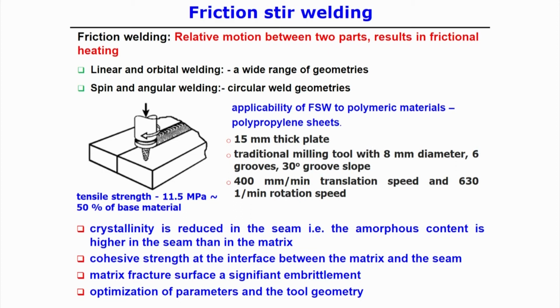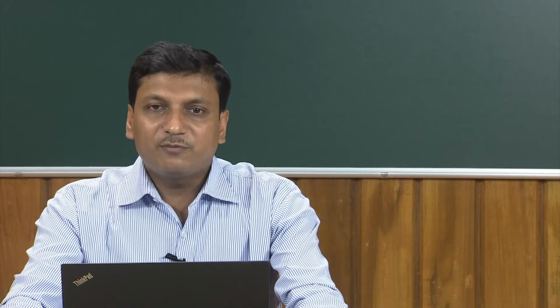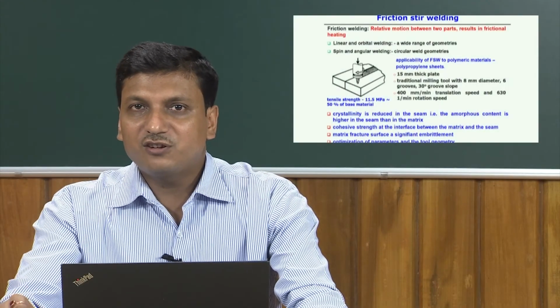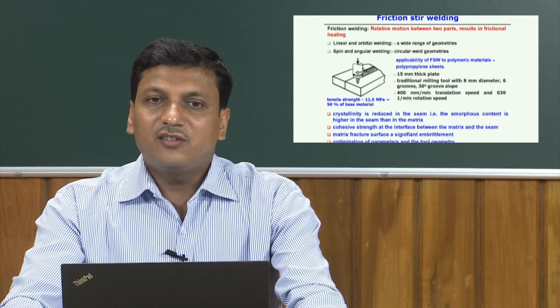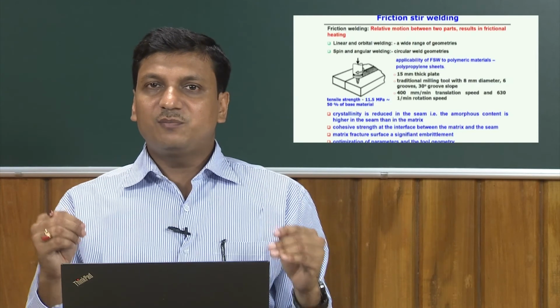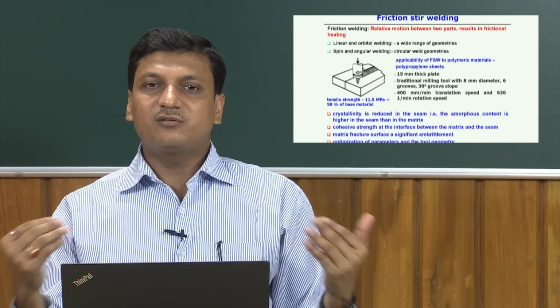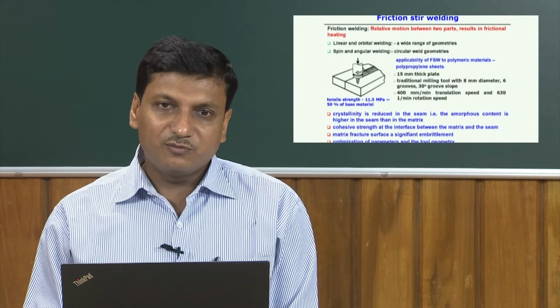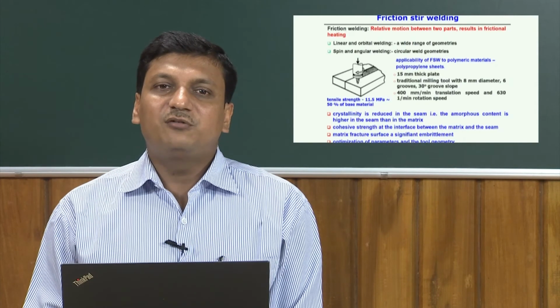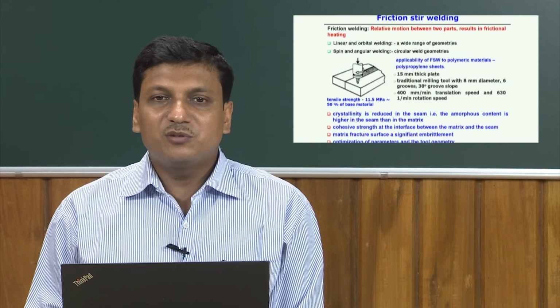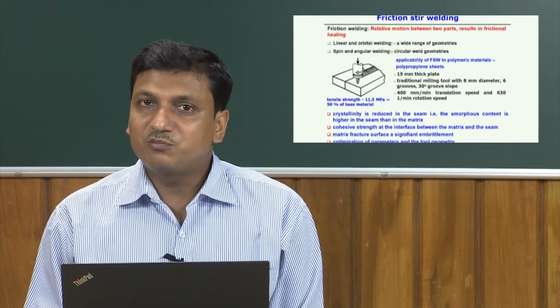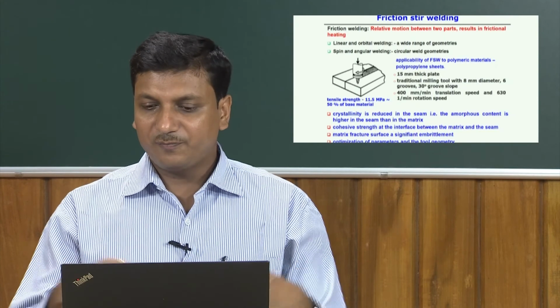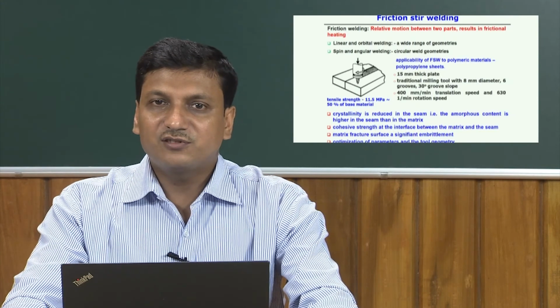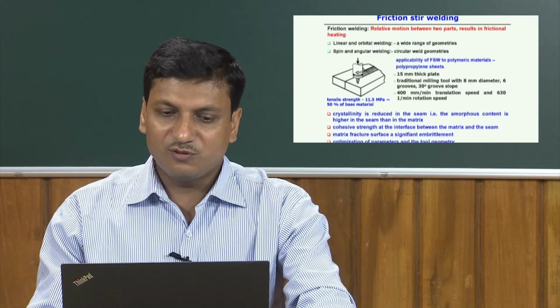At the interface between the matrix and the seam we can find the cohesive strength, and on the matrix fracture surface we can find significant embrittlement. These are the typical characteristic behaviors we can find for friction stir welding of polymeric material. But definitely, to achieve a good weld joint strength, there is a need for optimization of the parameters and, of course, optimization of the tool geometry. Further investigation on this process is required specifically for polymeric material.